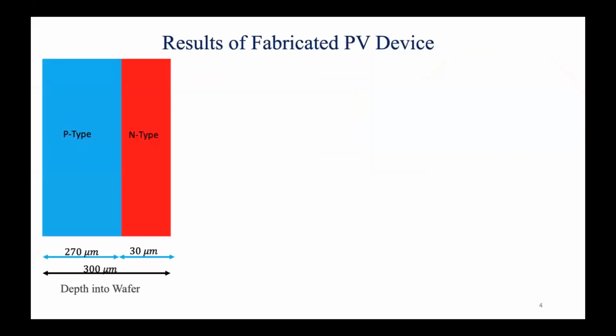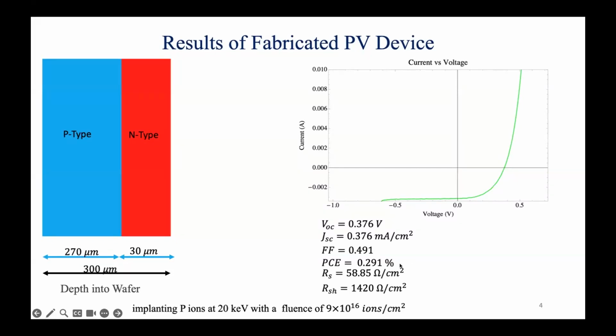The first device that we fabricated was a simple PN junction. Here we had a 300 micron wafer, and then we implanted P ions at an energy of 20 keV with a given fluence. With these parameters, we got an efficiency of about 0.291% as our power conversion efficiency.